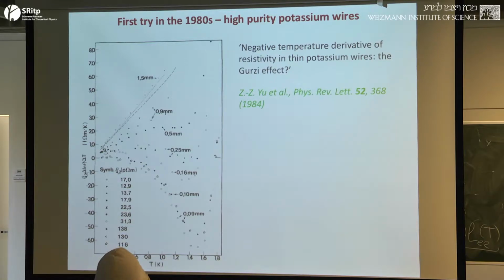In other words, the resistivity went up as the temperature went down, and therefore they thought, well, maybe we've seen the Gurzhi effect. That's the diameter of the wire. So that's a 90 micron diameter wire, radius or diameter, I can't remember. And they're increasing the diameter of the wire, and they're seeing that as they increase the diameter of the wire, they're going from a rising resistivity as temperature goes down to a standard one.